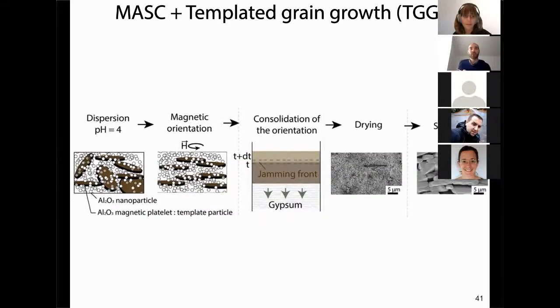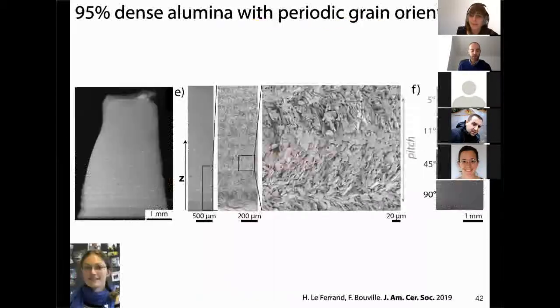And I definitely don't have time to go through the process. So we just used an old ceramic trick that is called templated grain growth. This time we use sintering kinetics to obtain very large grains in the end. But because we can control the orientation of the particles at the beginning, what we obtain, this is just an optical microscope image of an almost dense alumina sample, sintered naturally, without pressure. And you can see these shiny bands are where you see the platelets facing you.